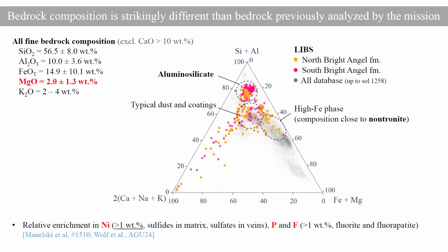The first thing we see is that this composition is strikingly different compared to the bedrocks that were previously analyzed during the mission, in the sense that it is relatively high in silica and has a very low magnesium content. If we look at this ternary plot of different major oxides, we have our measurements in the northern area in orange and the southern area in pink. We can see that the Bright Angel Formation plots relatively far from the gray clouds of higher iron and magnesium, so mafic rocks that characterize most of our traverse so far.